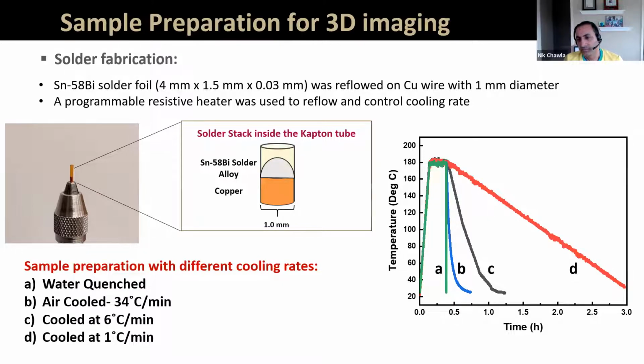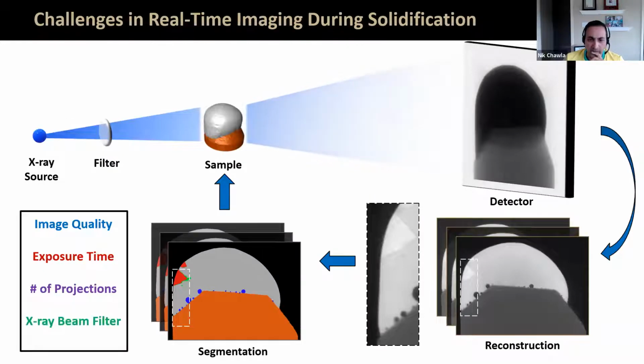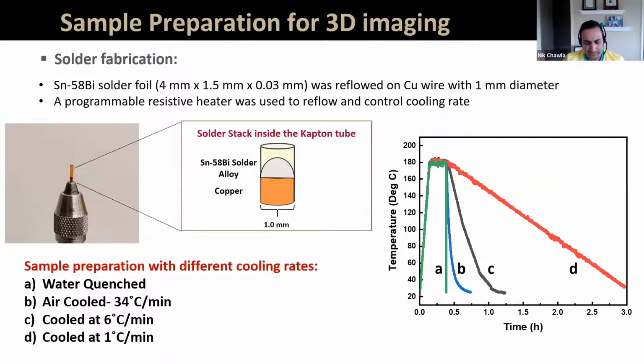And you have shown that the time resolution is like 0.4 second, right? So can we go beyond that, like in microseconds? Yeah, you can. Again, there is that trade-off between quality of the image and how fast you can scan. So I'll stop sharing here so I can see all of you better. The faster we scan, the less time we have for exposing the sample. That's where the synchrotron comes into play, because you have very large flux, you can get away with lower exposure time.